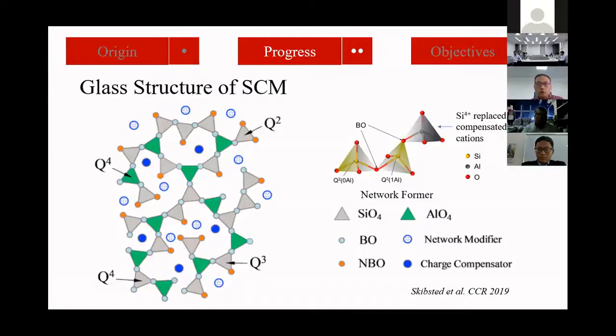The glass is made of so-called network formers, the tetrahedra of silicon oxide or aluminum oxide. This connected network is also modified by so-called network modifiers, or in other words, alkali cations like calcium, sodium, or potassium, and these cations break down the connected network and increase the reactivity of the SCMs. This is a very important concept in glass chemistry: the non-bridging oxygen, shown here in orange color, coordinated with the alkali cations, gives the SCM high reactivity, and the non-bridging oxygen per tetrahedron is used as an index to evaluate the reactivity of SCM.